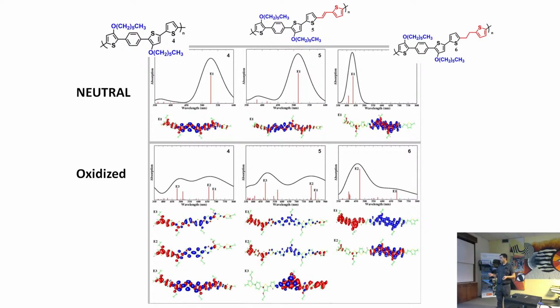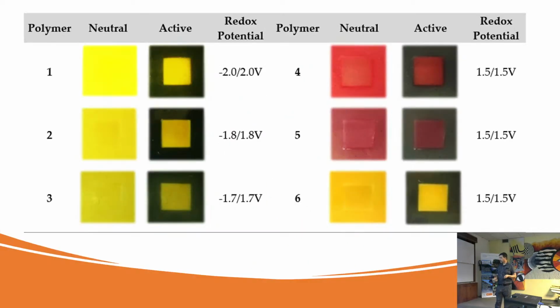But if we break the conjugation, then what happens is that you have the HOMO in here, and then in the LUMO you have a charge transfer for the other part. And this will produce an electronic transition that is now around 430 nanometers and brings the yellow. Okay? So at least yellow color could be achieved with this polymer 6.